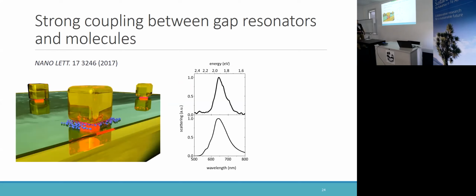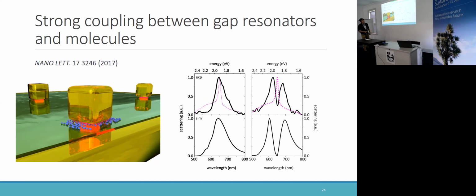So here, in this case, we place some dye molecules. Here it's not 2D semiconductors. We place some dye molecules between the nanocube and a mirror here. So here, that is the resonance of the single nanocube on the gold film. You can see it's just a gap resonator. It has the resonance here. Here's experiment and simulation.